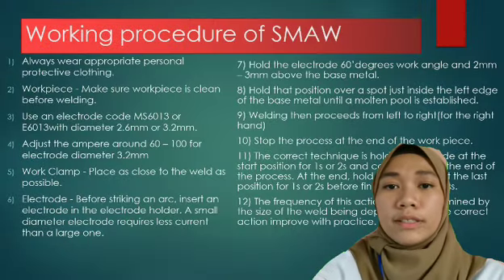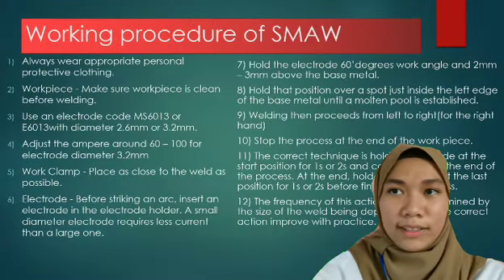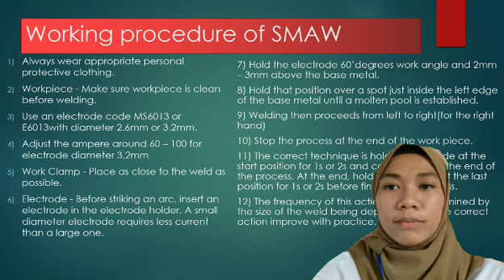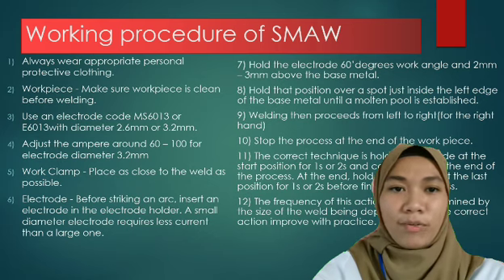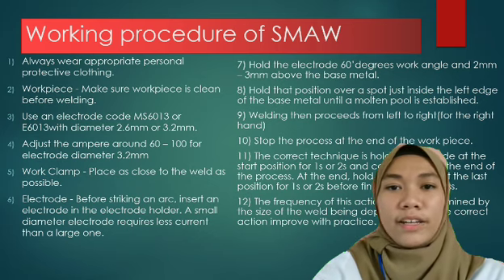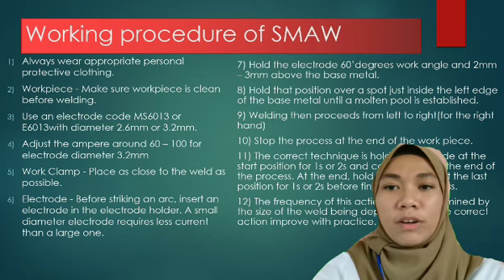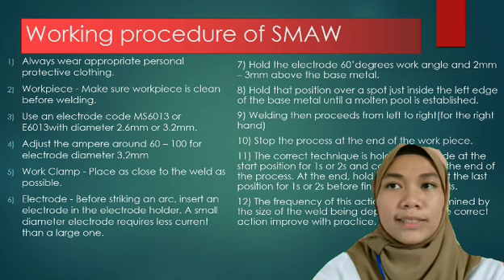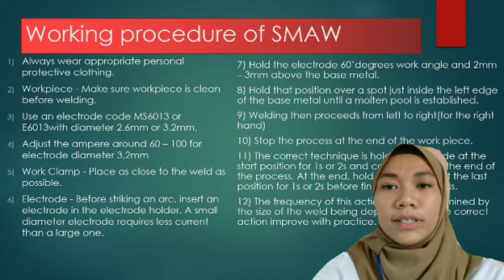Working procedure of shielded metal arc welding. First, always wear personal protective clothing. Second, make sure the workpiece is clean before welding. Third, use an electrode code MS6013 or E6013 with diameter 2.6 or 3.2 mm. After that, adjust the ampere around 60 until 100 for electrode diameter 3.2 mm. Work clamp: place as close to the weld as possible.